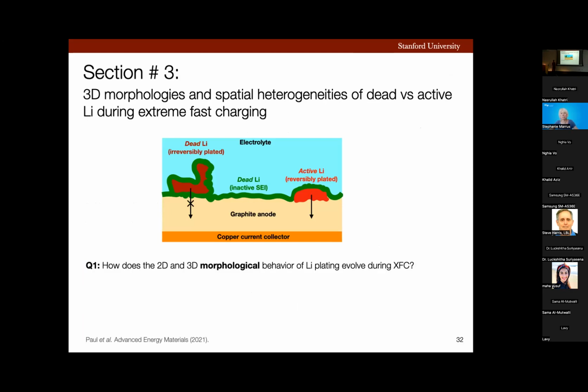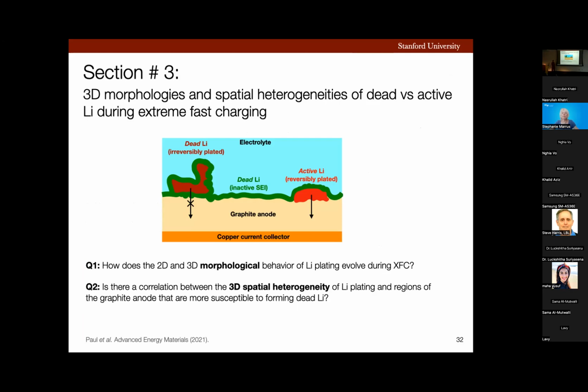In this work, I asked, how does the 2D and 3D morphological behavior of lithium plating evolve during fast charging? And is there a correlation between the 3D spatial heterogeneity of dead versus active lithium and regions of the graphite anode that form more dead lithium as compared to the other regions? And if there is a correlation, where are the regions that form dendrites, which degrade battery performance?